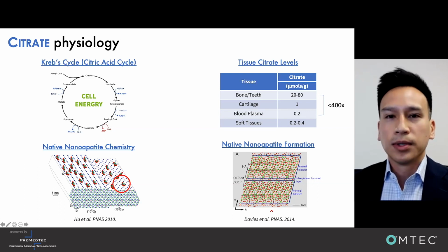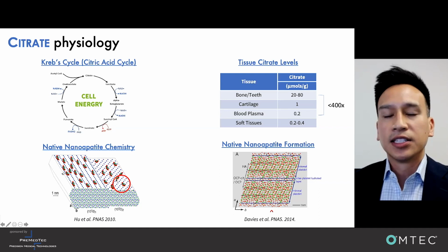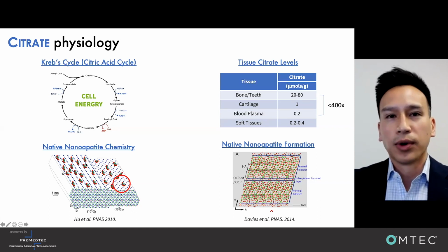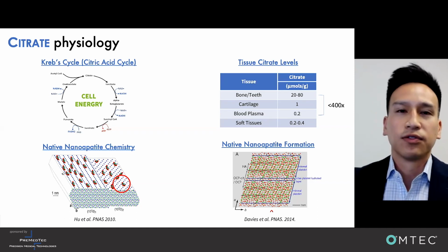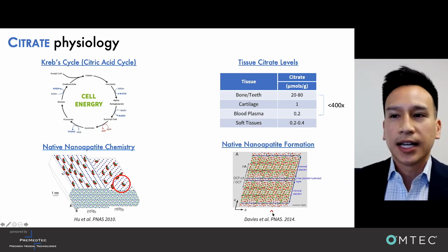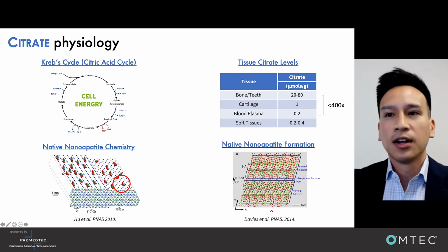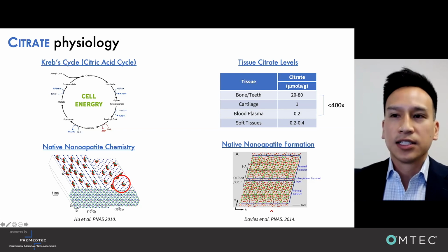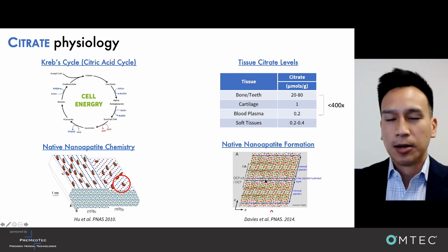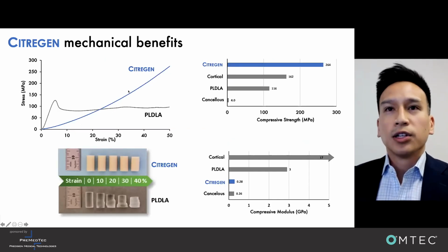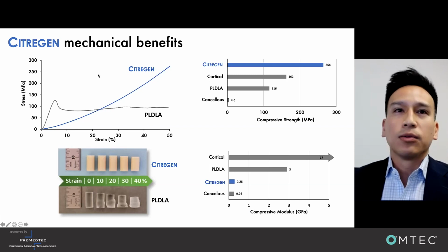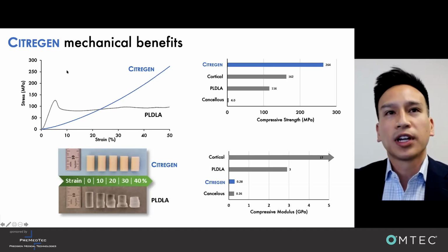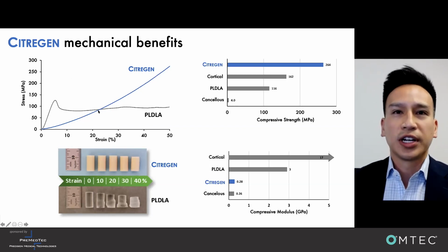One group in 2010 noticed that the citrate molecule was found bound strongly to the surface of nanoapatite, and it restricted the apatite growth in one direction and allowed it to grow in another direction, forming plate-like structures. A second publication in 2014 verified that the nanoapatites were actually bound together through a hydrated layer of citrate, giving bone its unique properties. So looking at the material design now, once it's composited with ceramic, we're looking at these compressive stress strain curves here.